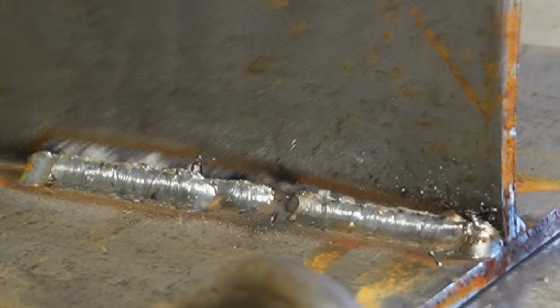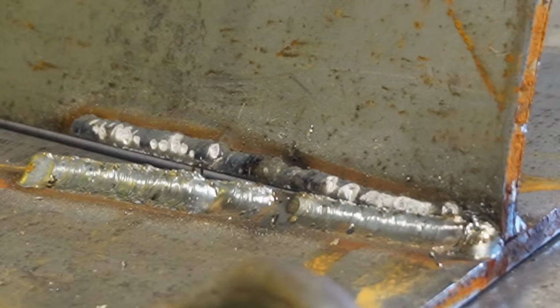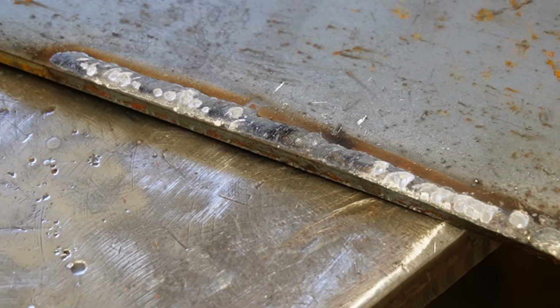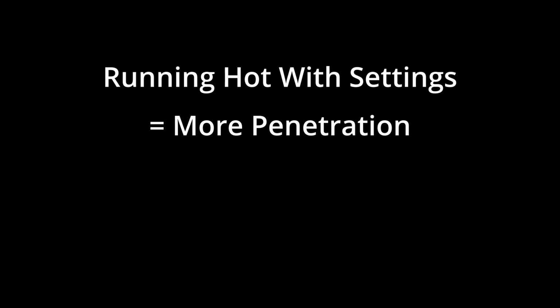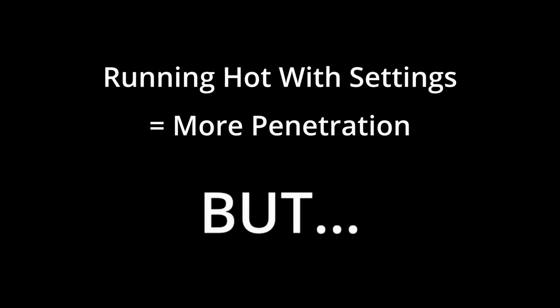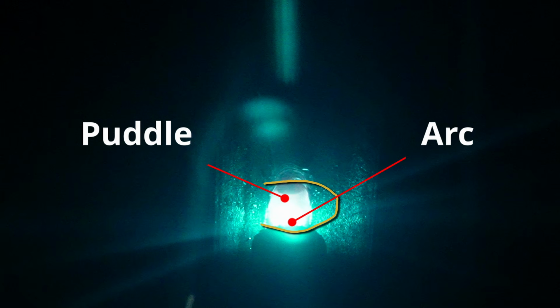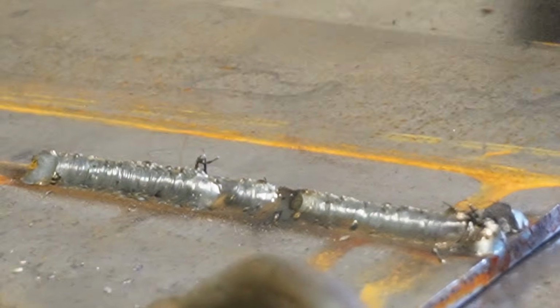The biggest problem with downhill welding is that it's usually not a very strong weld and it usually lacks penetration. So running hot with your settings helps you get more penetration, but since you're running hotter, the puddle is more liquidy and watery, so you gotta travel fast to stay in front of the puddle when gravity is pulling it down. So when you're traveling down the joint, you always want the arc to stay on the leading edge of the puddle so the puddle doesn't run down in front of the arc, and that's what causes lack of penetration.